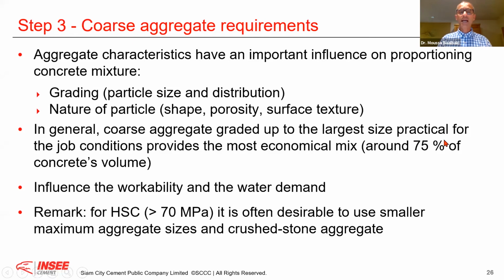And at the same time, I want to say that when you design high-strength concrete, okay, it's better to go with a smaller size of aggregate. Because in high-strength concrete, very often the amount of fines content in your mix is high. You have more than 400 kilograms of cement, because you are targeting more than 70 megapascal. Therefore, if the specific surface of the coarse aggregate is increasing, it is not a problem. Because when you reduce the coarse aggregate size, you increase the specific surface. But it's not a problem because you have enough paste. Your cement content is high.